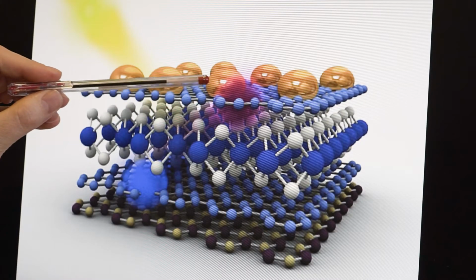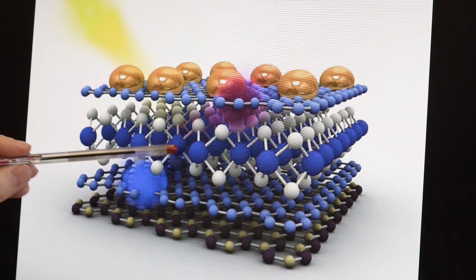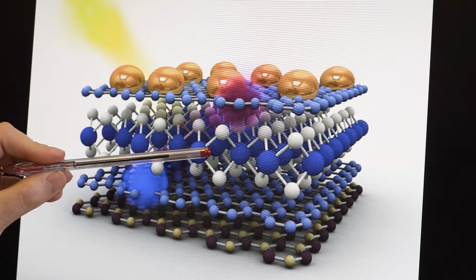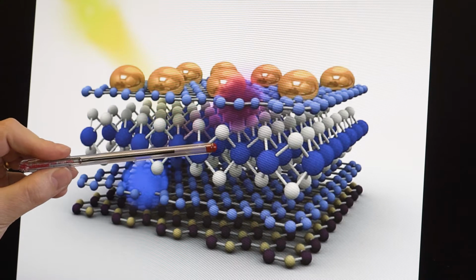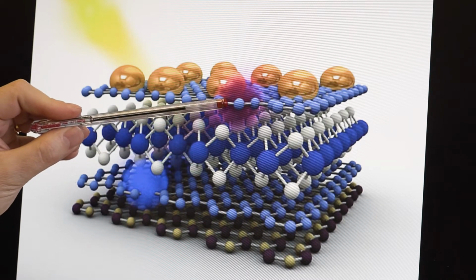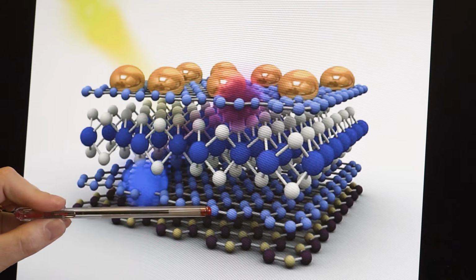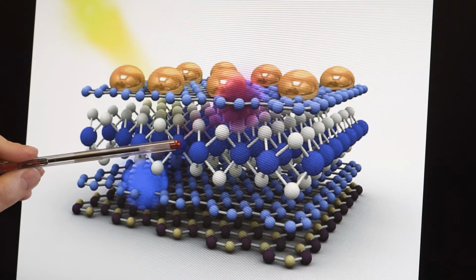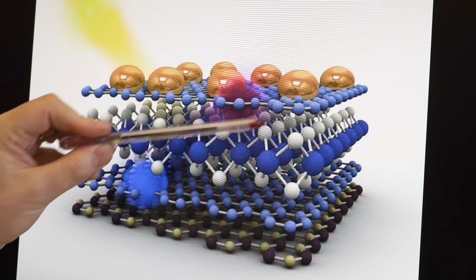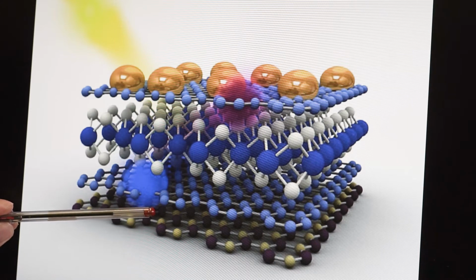The device works in a very simple way. You shine light, the metallic nanoparticles concentrate light on the transition metal dichalcogenide, and when this light is concentrated there, it produces two charges. One charge goes into the top graphene sheet, and the other charge goes to the bottom graphene sheet. So the graphene acts here as contacts to extract the charges from the transition metal dichalcogenide. So you know that light has arrived to the device when you see charges moving on the two graphene sheets. And this is something that you can detect because it's like an electric current.